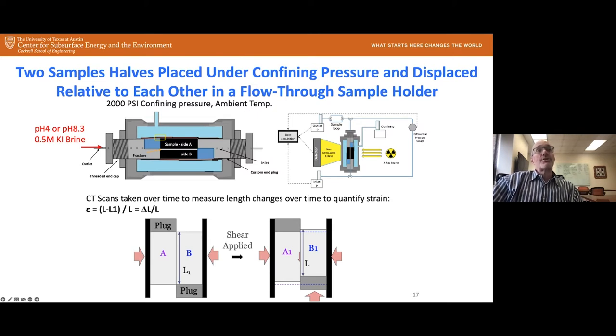This sample holder then, or this triaxial flow cell, we purge it after we apply this strain. We purge it or push through it a brine. It's a 0.5 molar potassium iodide brine. The iodide is used as a contrast agent for the CT imaging. And we used either pH 4 brine, and this was done with nitric acid. We didn't have elevated temperature capabilities in this triaxial cell holder, so we did not use CO2 to create this pH, but nitric acid. And then we also had a reservoir simulated brine where we crushed up rock, this Bandera gray sandstone, equilibrated it with the water over a couple weeks, and then just decanted off the water, and it was at 8.3, and used that to flush it through. During the experiment, we loaded this into an industrial CT system, and then we imaged that over time to look at the movement or the relative movement of these two halves.